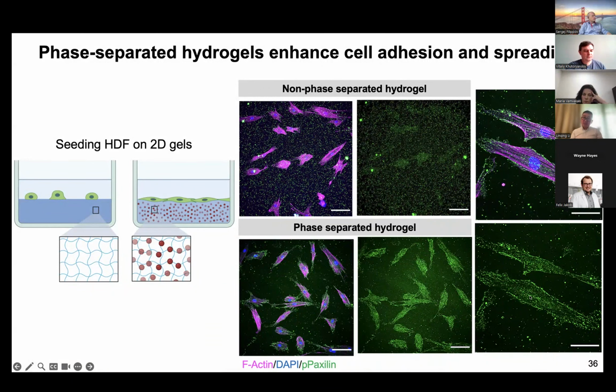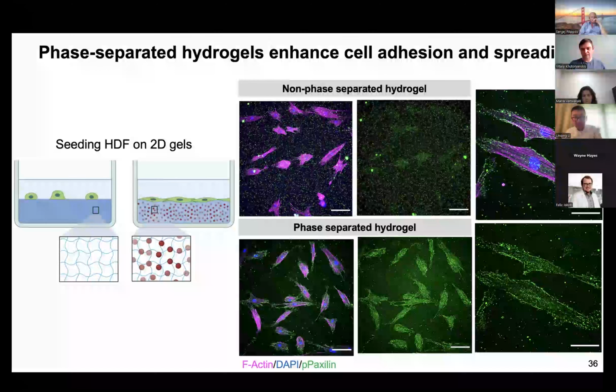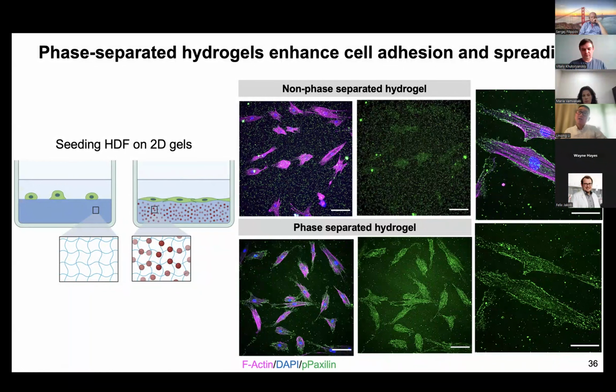Now this seems contradictory to the traditionally established view, but if you think again, it's not the bulk hydrogel properties that control cell behavior. It is actually the local properties that dominate. The local environment, the local stiffness, is more important for cells to sense. So we believe in this case we have locally stiffer regions, which promote cells to spread better and also have defined focal adhesions. Again, this is consistent with what research has reported. However, because this hydrogel is unique compared to the traditional hydrogel, that's why we're seeing this unique behavior.